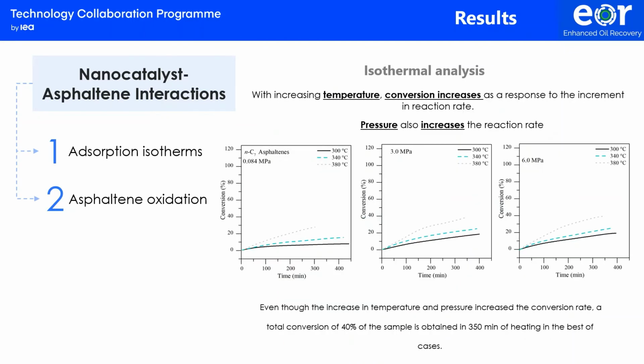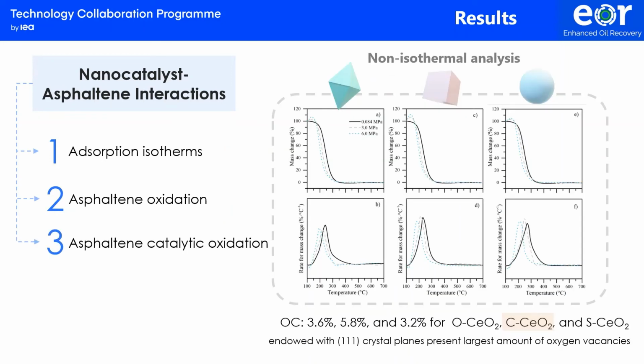As for the isothermal analysis, it is observed that with increasing temperature and pressure, the reaction rate improves for the asphaltene oxidation. However, a conversion of 40% of the sample is obtained in 350 minutes of heating in the best of cases. On the other hand, the catalytic effect of the material is noted in the reduction of the decomposition temperature of the asphaltenes.